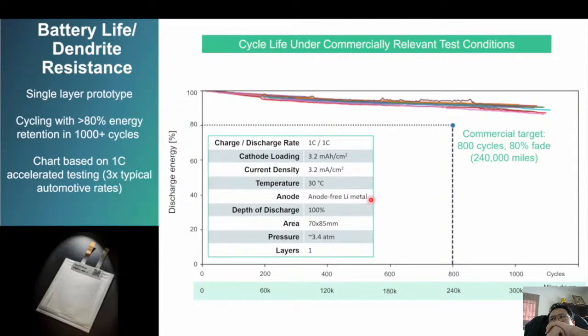We're using the anode-free lithium metal anode configuration that I've described, going full depth of discharge over the full commercially relevant areas. Pressure is something I'll talk more about in a minute, but these tests are done under relatively modest pressure on single layer cells. So I think this was a pretty exciting proof that the materials and the processes that we use to make these materials are really capable of withstanding real world conditions, or even more aggressive than real world conditions here.